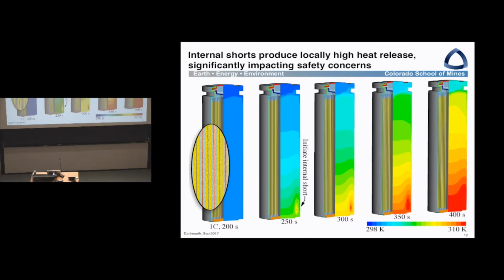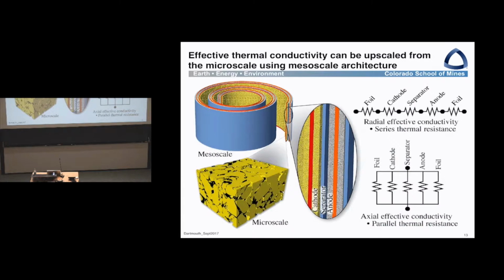So we're quite keen to know what happens if, for example, we have a dendritic short someplace in this battery, how that thermal response propagates and leads to accidents. What I'm showing here again at the macro scale, or micro-macro scale, in a jelly-rolled structure is if I look at the effective conductivity radially, then these foils have almost no effect because the thermal resistance of those metals is very low. There's basically no resistance. So the radial heat conduction is driven essentially entirely by the conduction of the electrodes. But in the axial direction, it's quite different because now these metal foils, the current collectors, can channel heat axially much, much more efficiently than radial.